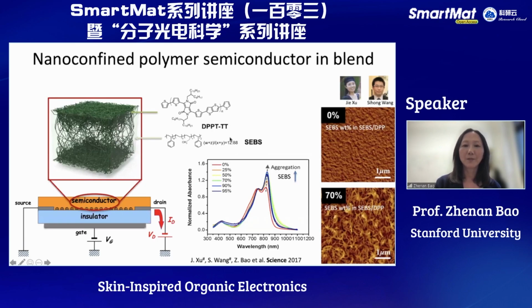And next, we have been thinking about how we can come up with a way to not sacrifice the charge carrier mobility. And staying with conjugated polymer is important. But these conjugated polymers, even as a neat polymer, normally form the morphology shown on the right by the AFM, essentially featureless. There is some disorder, but you don't see any distinct morphology or structure formation. We hypothesized that if we can have some kind of network nanostructure, then these nanostructures themselves could potentially allow a fishnet structure to allow better stretchability.